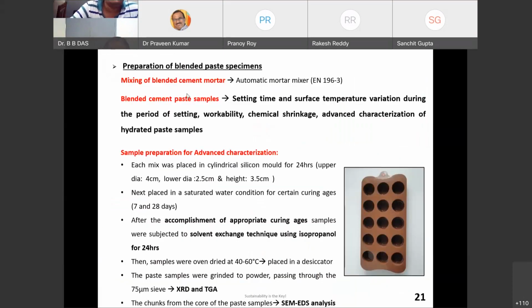Then similarly, the preparation of the blended paste specimens is also done. Then mixing of blended cement mortar through the automatic mortar mixer, the only difference being that the setup is different. What measurements were done actually? Measurements were done for setting time, surface temperature variation, workability, chemical shrinkage, and also advanced characterization of the sample. I'll talk about the hydration and microstructure.